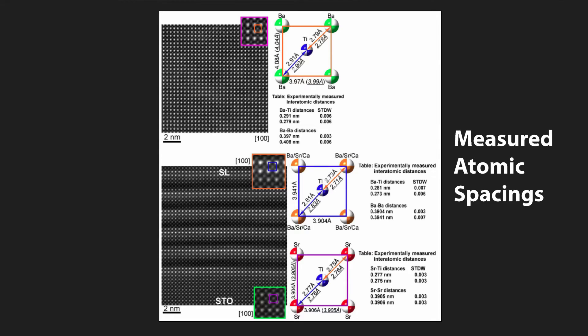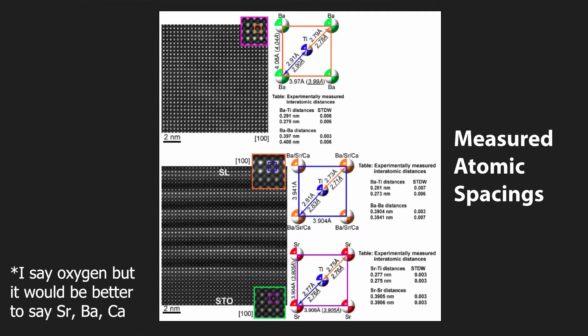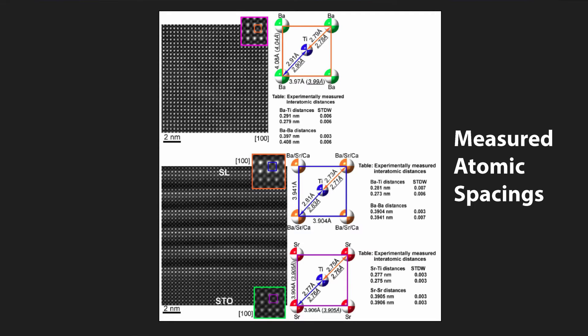However, this makes significant differences to the materials in many ways. One key component is the atom's spacing. You could imagine that all of the oxygen atoms would line up in these materials, but this is not the case in their natural form. The oxygen atoms have different positions, but when they are layered on top of each other, their interactions between the layers tug and pull the other atoms until all of the oxygen atoms do line up. This pulls and pushes some of the atoms around, straining the lattice, which in turn significantly improves the performance of these materials as a PV cell, because it enhances the inbuilt electric field.